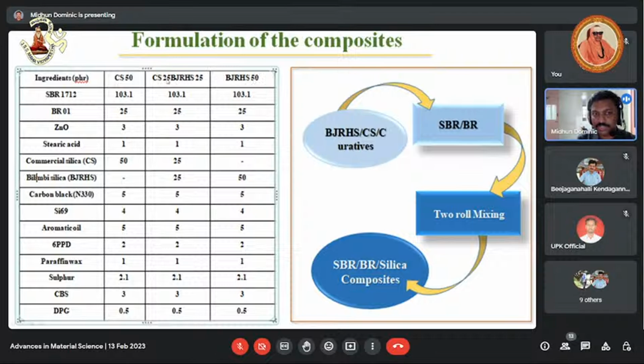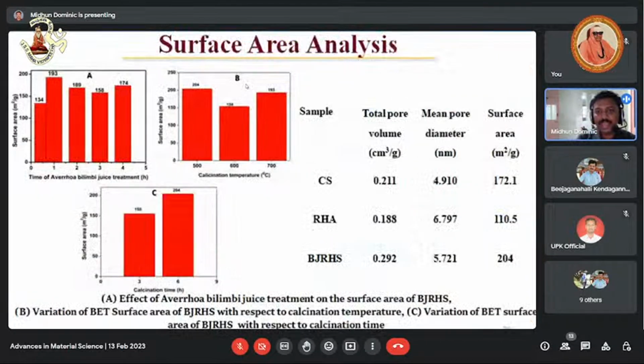So we have 3 composites. One is with commercial silica, one is a 50-50 mixture of commercial silica and BJRHS, and one is BJRHS 50. We have to know the properties of the rubber composites, and look at the surface area. Commercial silica has a surface area of around 172 meters squared per gram.